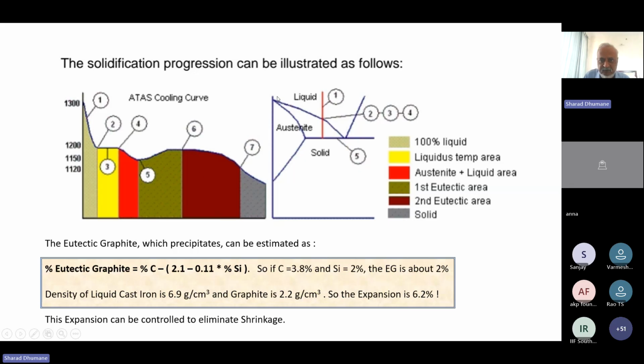So the same thing when we see on the phase diagram, you can see the material is cooling down like this. So this cooling down is basically what we see here. Okay. So the point 1 is the point 1 here. Point 2, 3, 4, all these points are here. So this is your liquidus point, and at this point solidification starts. That is why the temperature is decreasing over time, and as the time increases, temperature is decreasing.